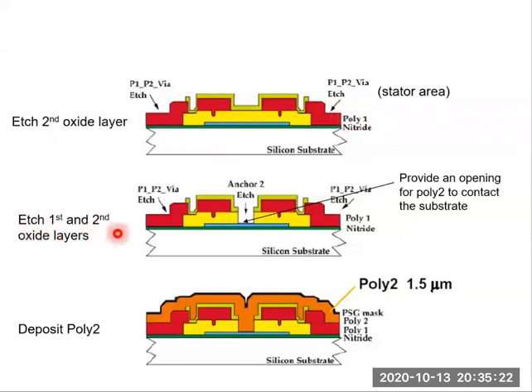Then etch the first and the second oxide layer. This green layer and yellow layer are etched. We call this anchor 2 etch. This etch provides an opening for poly 2 to contact the substrate. Right, it's very clear. In the next step, we deposit poly 2.